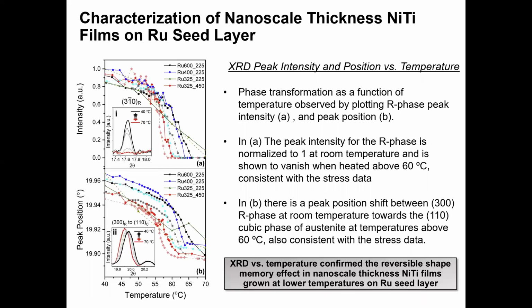So, picking back up, we're just looking at some additional characterization of the same films that we were talking about. This is XRD peak intensity and position versus temperature. The phase transformation as a function of temperature was also observed by plotting the R phase peak intensity in A, and then peak position in B. The peak intensity for the R phase at room temperature was shown to vanish completely when heated above 60 degrees, and is consistent with the stress data, confirming that the transformation into this high temperature austenite phase was happening in each of these films.